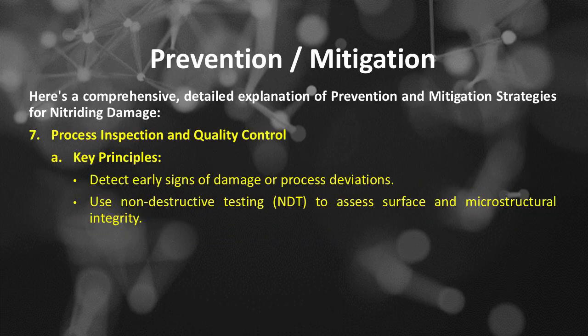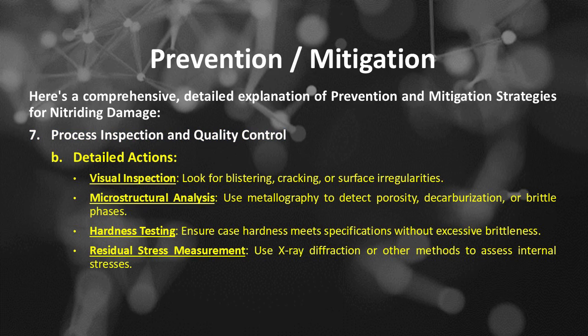Number 7 of prevention and mitigation strategies for nitriding damage is process inspection and quality control. The key principles include detecting early signs of damage or process deviations, and using non-destructive testing, or NDT, to assess surface and microstructural integrity. Detailed actions include visual inspection: look for blistering, cracking, or surface irregularities. Microstructural analysis: use metallography to detect porosity, decarburization, or brittle phases. Hardness testing: ensure case hardness meets specifications without excessive brittleness. Residual stress measurement: use X-ray diffraction or other methods to assess internal stresses.